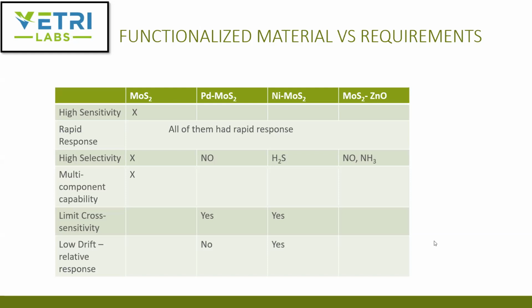So the palladium and the nickel were chosen as the best material for limiting the cross-sensitivity. And drift-wise, there was not much study, primarily because they tested in seconds. Typically, sensors take longer time to drift. But over the time of the test, I would say that the nickel moly sulfide did show more repeatability. And the palladium-based with the nitric oxide selectivity did not show as much drift response. So I think that was the end of the presentation.